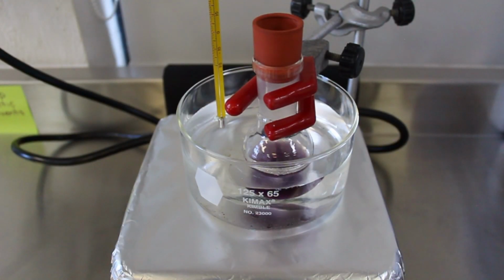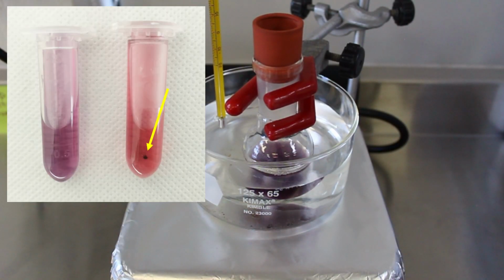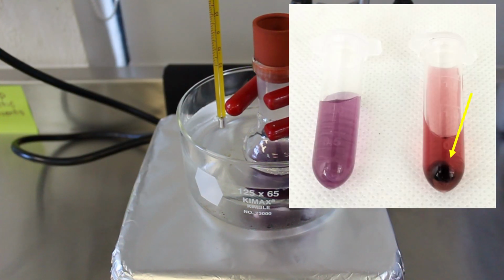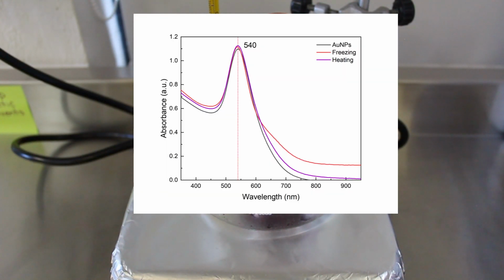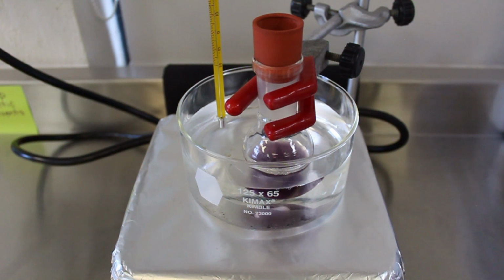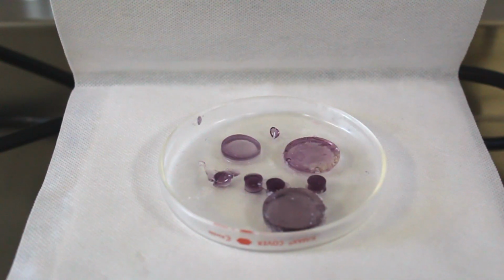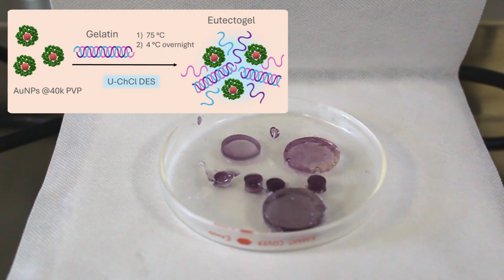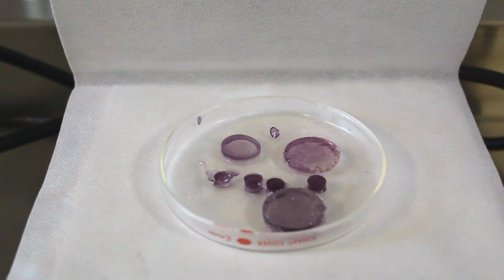The prepared colloid showed great stability to solar exposure, centrifugation, and temperature changes, showing no signs of agglomeration, in contrast to particles synthesized in water using the same methodology. Such stability allowed us to prepare an eutectogel containing the gold nanoparticle.